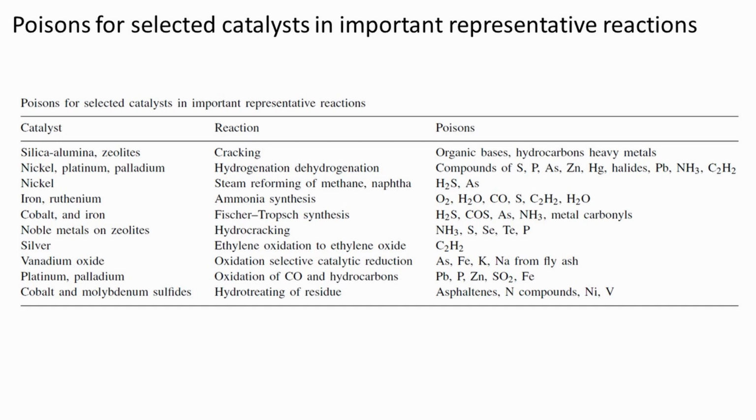Metal compounds like nickel, lead, vanadium, and zinc are poisons in automotive emission control, catalytic cracking, and hydrotreating. Acetylene is a poison for ethylene oxidation, while asphaltenes are poisons in hydrotreatment of petroleum residual.